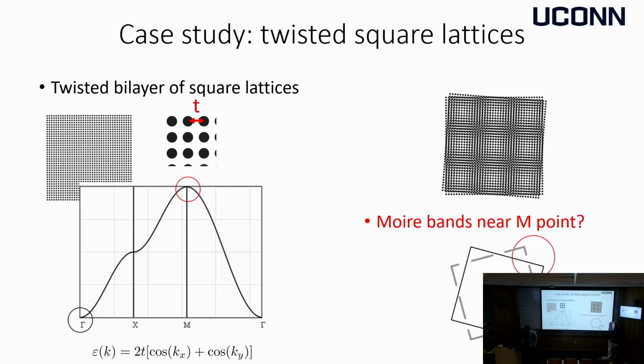And on a hexagonal lattice, there's also an M point. There are actually three M points. And there have been works from the Bernevig group, which have seen the same thing happening, but on a hexagonal lattice. So there's the same effect, but what you get there is three quasi-one-dimensional moire bands, which don't talk to one another. They're quasi-one-dimensional specifically because the lateral coupling is forbidden by the same effect. Now, the K point would be different, but there will still be consequences of the symmetry at any high symmetry point. One just needs to figure out which consequences exactly.